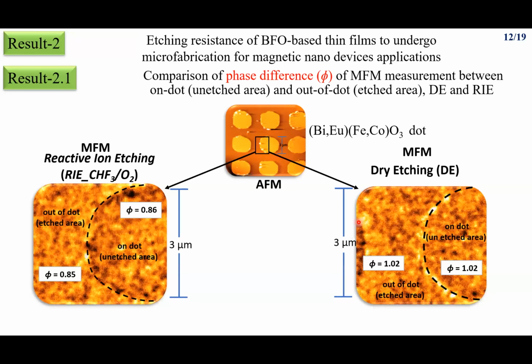So now the very important part, that is microfabrication. To study the magnetic damage during microfabrication, we considered our thin films and fabricated micro dots of 3 micrometers. You can see this dot area is covered with resist pattern, and the area outside the dot is simply bismuth ferrite film. So when this thin film with dots is exposed to etching gas, the dot area is covered. That means the dot area is safe, but the area outside the dot is not safe.